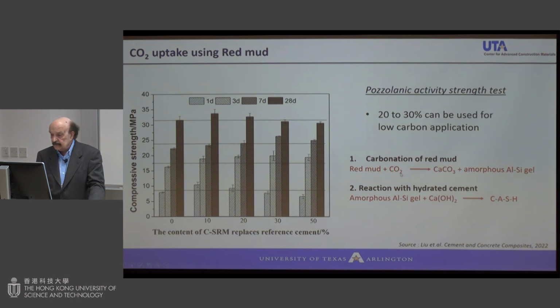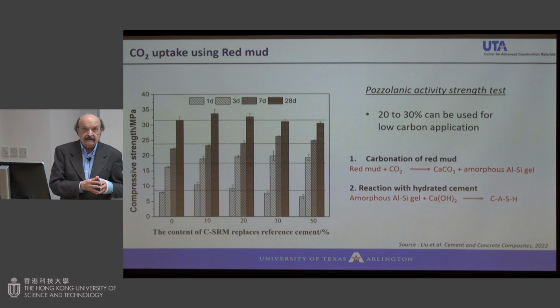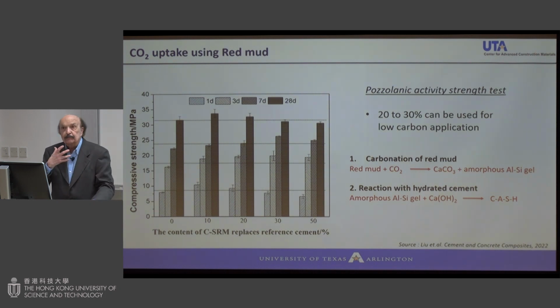So you have red mud and CO2, so you have calcium carbonate and this amorphous aluminum silica gel. And this amorphous silica gel acts as a pozzolanic material to produce CSH. So you have converted red mud, a waste material, into a pozzolanic material after carbonation. So you have absorbed CO2, that's a good thing.